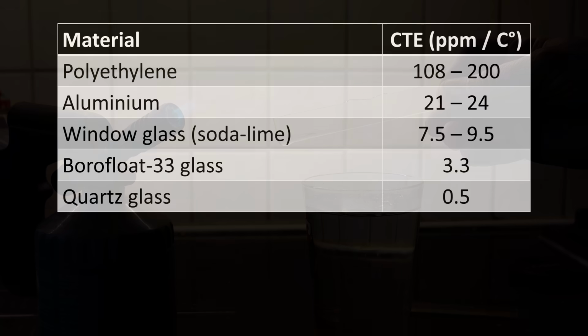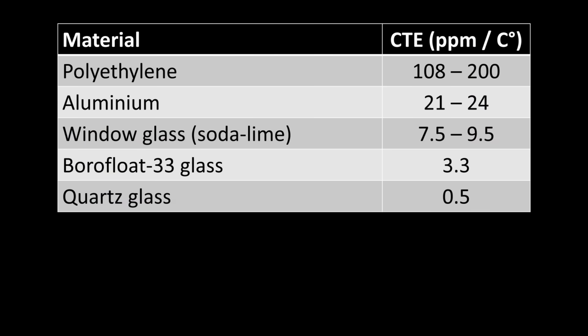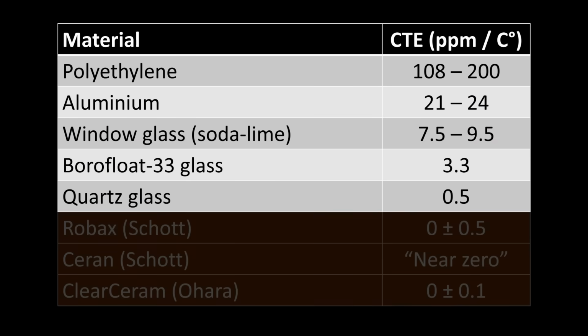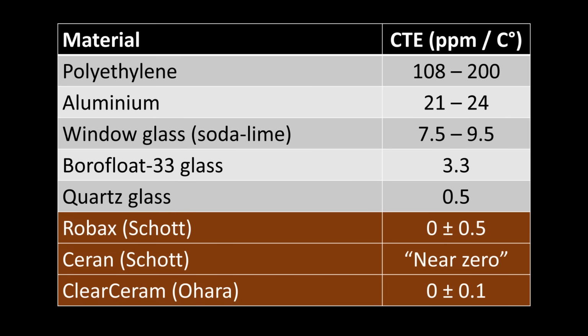But high quality quartz is quite expensive and difficult to make, and it's not as resistant to thermal shock as certain glass ceramics. Here I added the CTE data of a few glass ceramics like Robax, Ceran and Clearceram from their data sheets. And for these materials the CTE is generally specified as 0, plus or minus a specific tolerance. The actual value of the CTE is in the deviation it can have from the 0 value.